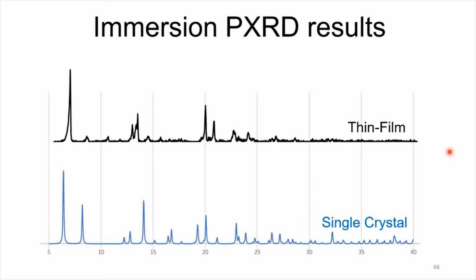And sadly enough, I don't have AFM results. We were finishing all this project when the quarantine started, but we did have the XRD results, PXRD. So on the bottom, you can see the single crystal simulated pattern from the MOF, the original MOF, and on the top the thin film. So this is just from the process of immersion.